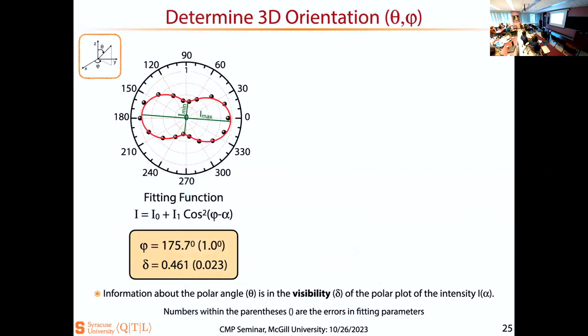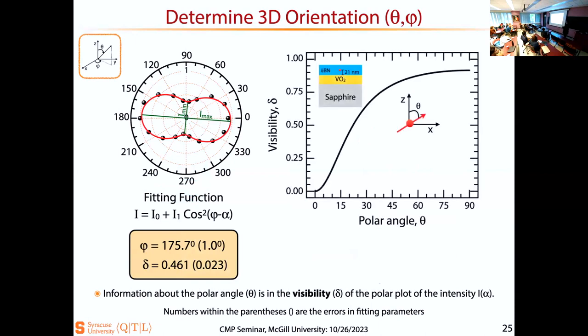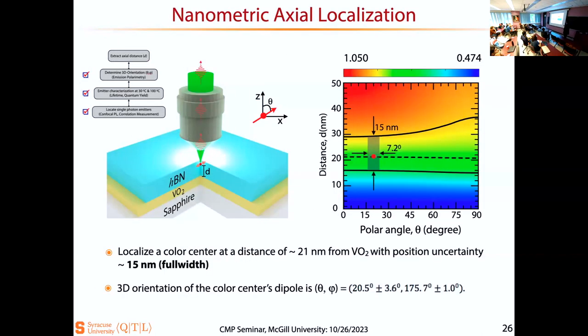And then we performed the experimental measurement. We didn't get a perfect dumbbell. We didn't get a circle. It means that it does have a good vertical component. And then using modeling, we were able to extract both the in-plane and out-of-plane dipole moment. We solved that issue.